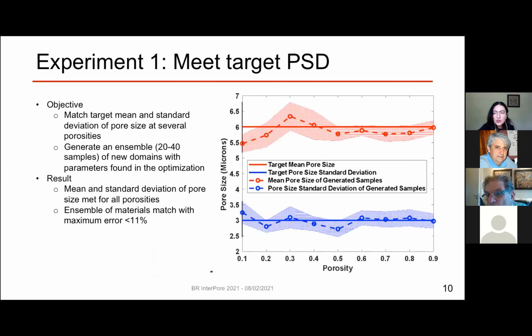So with these materials that we now can generate numerically, we did several experiments. In the first experiment, the goal was to match the mean and the standard deviation of pore size at multiple porosities. So we aimed for a mean of 6 micron and the standard deviation of 3 micron, and we generated 20 to 40 domains. And here you see the porosity is ranging from 0.1 to 0.9. The red one is the mean pore size. The blue is the standard deviation. The straight lines are the targets. This is what we want to hit: 6 in pore size and 3 in standard deviation.